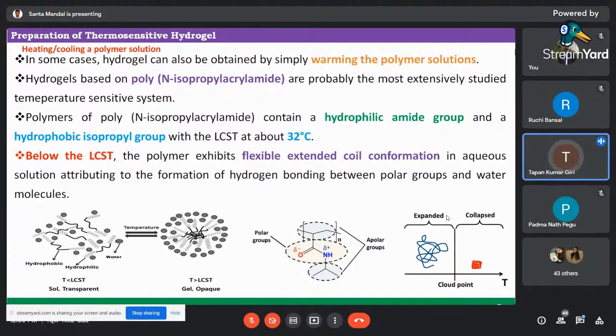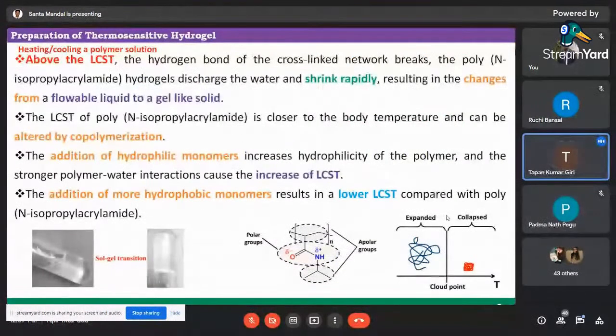You see the figure at less than LCST. Sol means transparent, hydrophilic portions are there, and there is hydrogen bonding interaction between the hydrophilic polymer and water. But as temperature increases, you see in the center, the hydrophobic polymeric portions are aggregated due to their attraction and ultimately convert into the gel structure. Next. Above the LCST, the hydrogen bonds of the cross-link network break. The poly N-isopropyl acrylamide hydrogel discharges the water and shrinks rapidly, resulting in a change from a flowable liquid